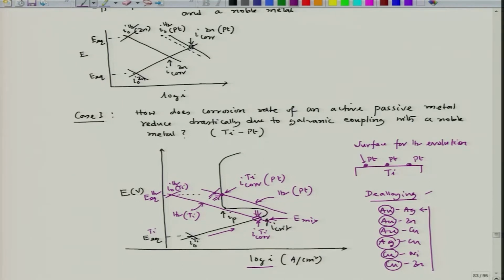This mechanism is not very simple, it is complicated. There are several such mechanisms. One of them says that both elements go into solution in the form of ions. Once both of them go into solution as ions, the ions with higher reduction potential would like to go back to the surface of the metal and get reduced, forming the pure metal, and that is what forms those dots.